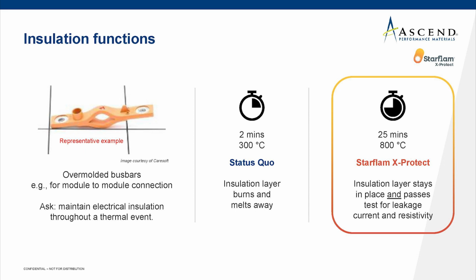Of course, if you would use a regular flame retardant PA66 and expose it to temperatures above your melting point, you would expose that bar after a very short period of time, like 2 minutes or so. The insulation layer would burn and melt away and expose the bar, which is a failure with regards to the ask. Starflam X Protect, in this case, we were able to expose it to a flame of 800 degrees C for 25 minutes. And after these 25 minutes, still the bar performed with the proper electrical insulation properties that you would expect from the virgin component.